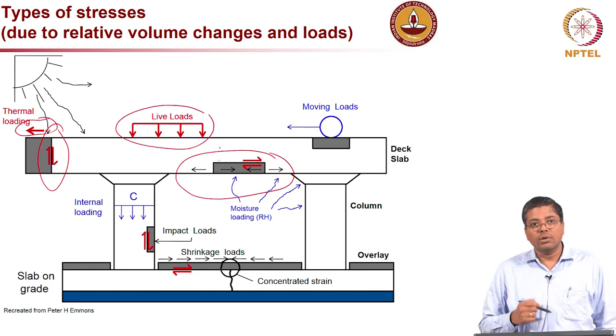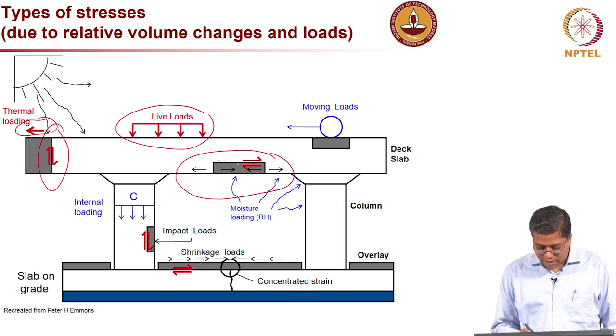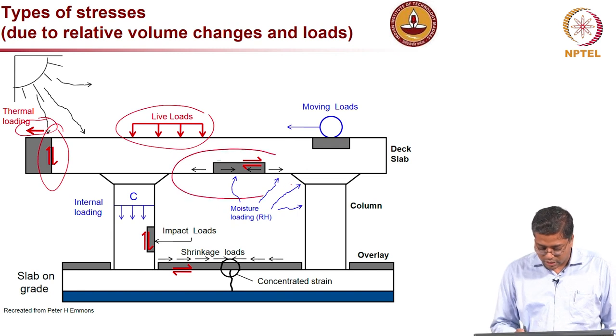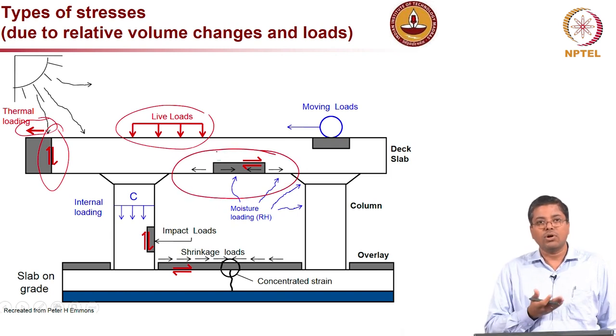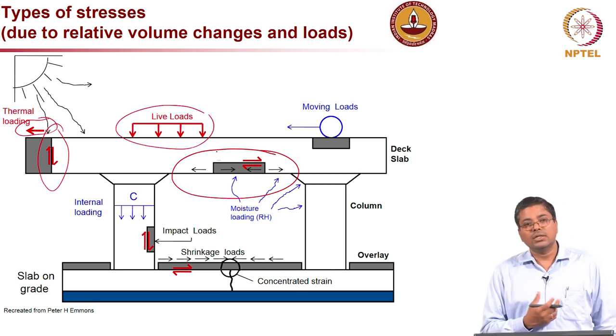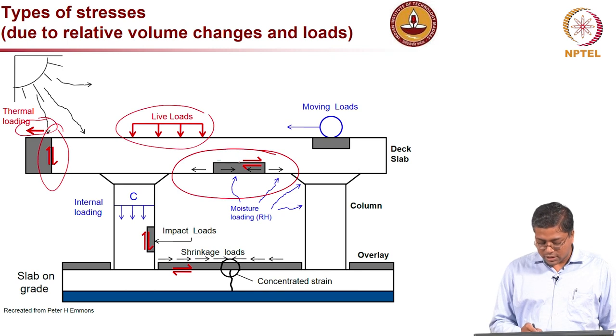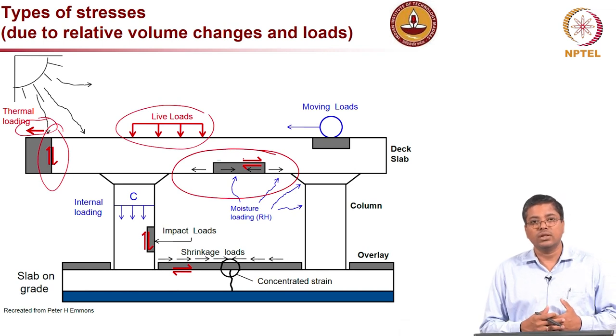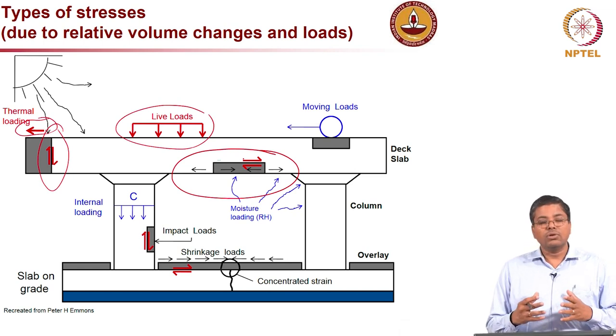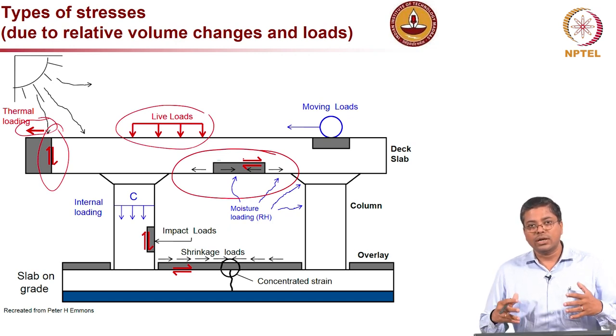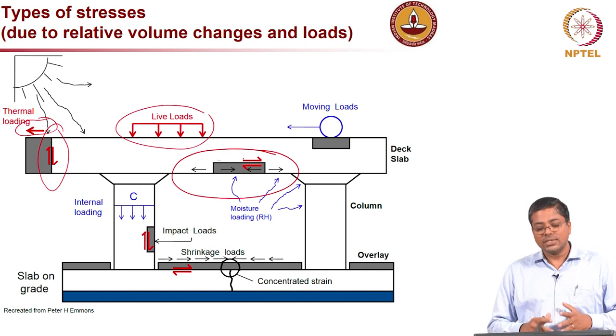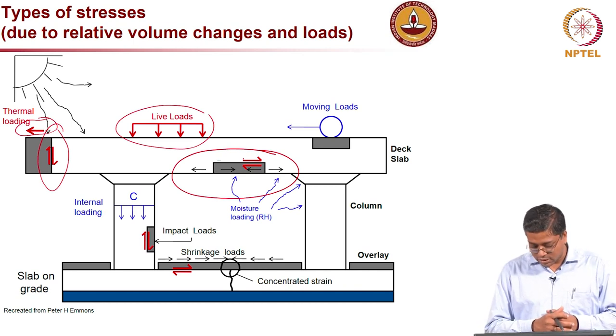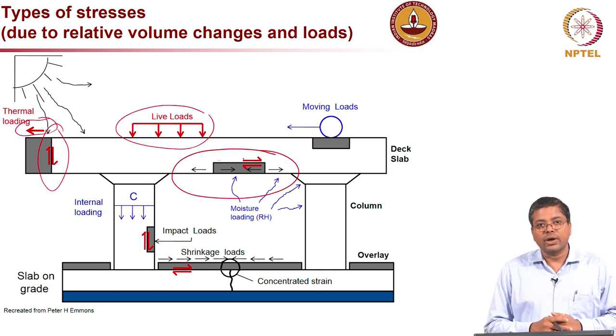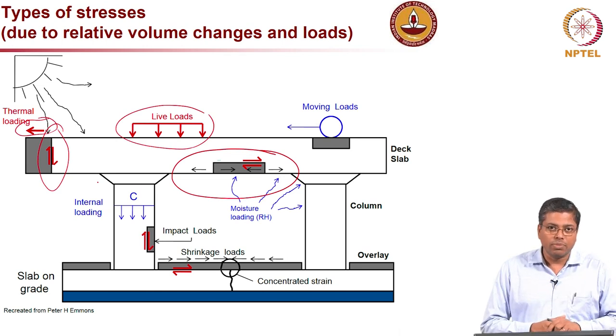And then when you talk about repairing, for example here in this case, if I am replacing some concrete at the bottom of a bridge deck, what are the things I should worry about? I must ensure that the red arrows indicate the shear bond, or the shear stress, between the existing concrete and the substrate. So you have to think about how compatible that material is, whether the new repair material is going to shrink as compared to the existing substrate. So, different strain compatibility; you have to look at many factors before just placing the new repair material.